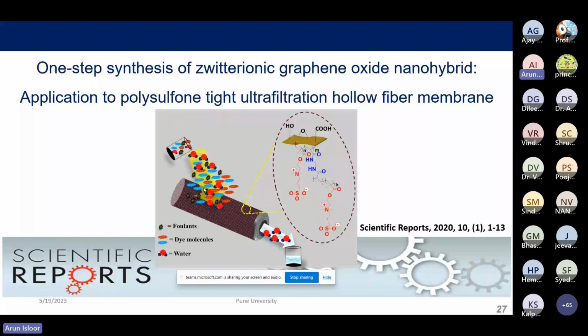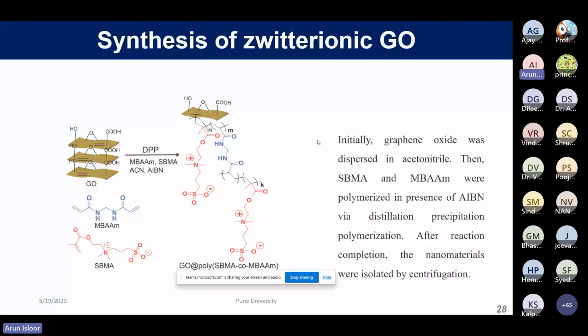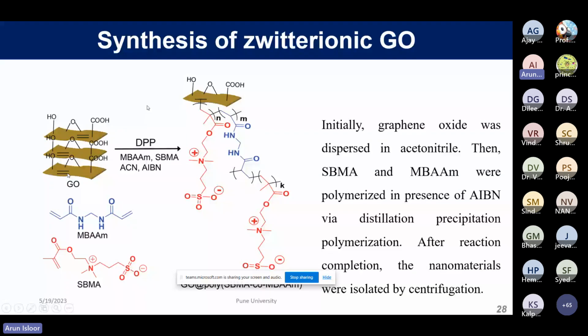So here in this particular strategy, we have synthesized the graphene oxide in our laboratory using graphite, treating with KMnO4 in the presence of sulfuric acid. And then the zwitterionic polymer nanoparticles were chemically bonded, which you can see here in the graphical abstract. The zwitterionic nanoparticles were chemically bonded on this graphene oxide sheet, the GO sheet. That was in the Scientific Reports paper in 2020. So this is the particular strategy. Here the GO was synthesized in our laboratory, and then the other two monomers are the same as in the previous work.